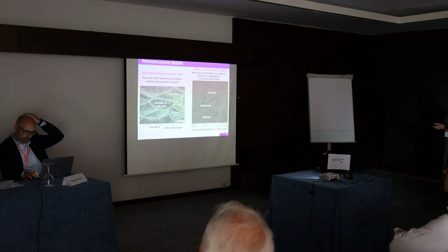Here we can see some microstructure details. We can see the melt pool microstructure. There is a fine zone. This is the microstructure in the scanning microscope. Then we can see the boundary of melt pools, and with high-magnification scanning microscopy we can see a coarse zone and also a heat-affected zone. In the microstructure there are some pores and also some micro-shrinkages, but not very many, though they are always present.